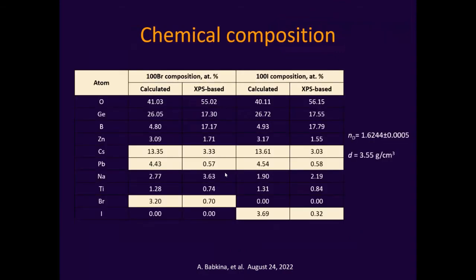Okay, so some chemical results. We, of course, studied the chemical composition of our glass, because the chemical composition that I showed you before is the chemical composition of the glass batch. When we synthesize the glass, a lot of elements volatilize out of the glass. So the final chemical composition of the glass is not the same as the chemical composition of the batch.